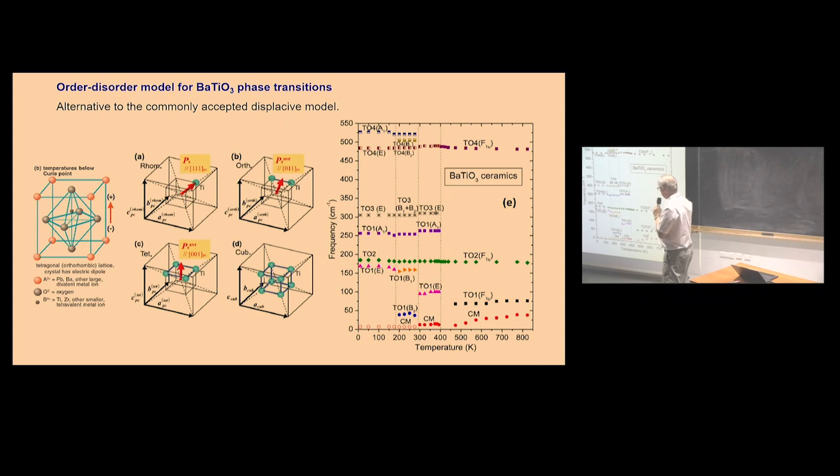This is phonon active in C direction. So permittivity is much lower. Here it is much higher, the permittivity in A and B plane. So in the next phase transition, you have again displacement in this direction. Then you can imagine that you have hopping among 2 positions. And finally, in rhombohedral phase, only displacement along 1 direction.